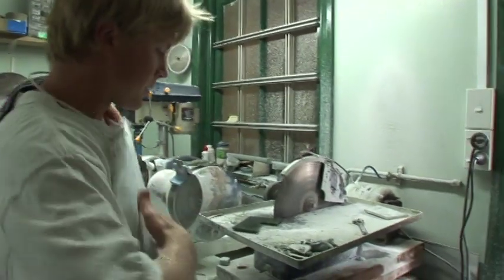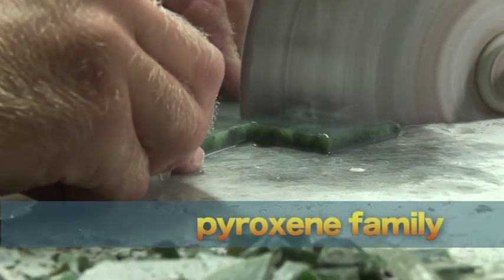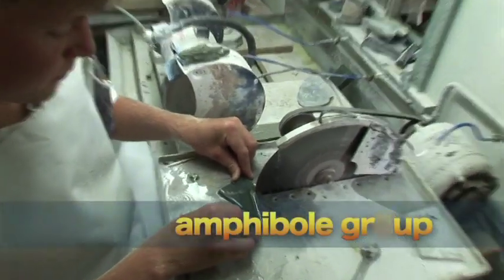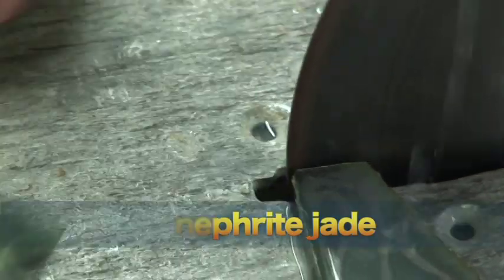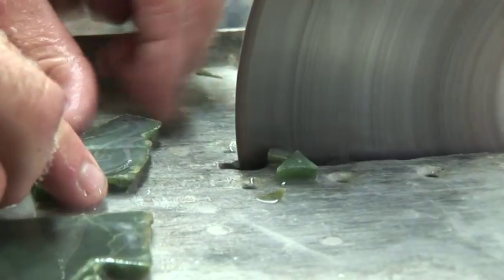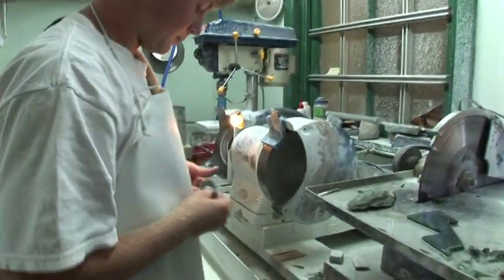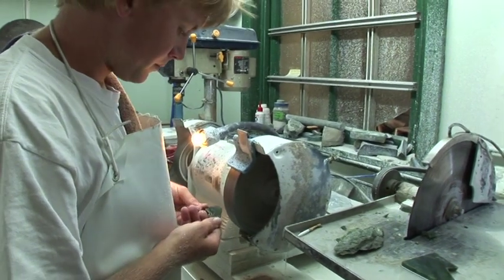There are two types of jade. One type is composed of the mineral jadeite, which is a silicate and a member of the pyroxene family — this type is often called jadeite jade. The other type is composed of one of two minerals belonging to the amphibole group, and this kind is called nephrite jade. Nephrite jade usually forms when two rocks of very different composition wind up side by side. During metamorphism, nature smooths out chemical differences through a process called metasomatism, producing a new layer of rock composed of tiny interlocking crystals of a single type of mineral. Jade can be used to create elaborate and intricate shapes because of its high fracture toughness — meaning it doesn't break very easily — and also because it's very resistant to scratching, around five and a half to six and a half on the Mohs hardness scale. These characteristics make it ideal for uses like jewelry and sculpture.